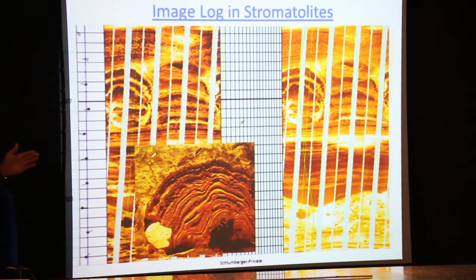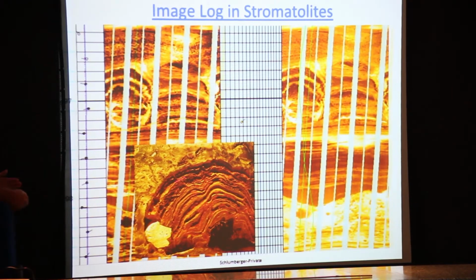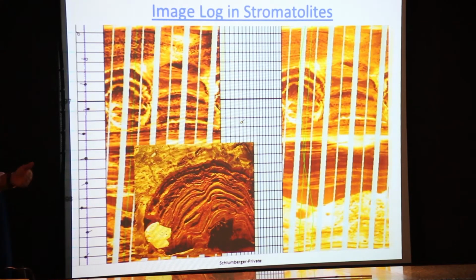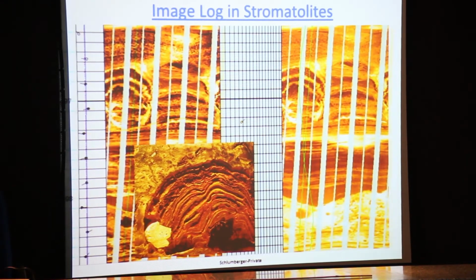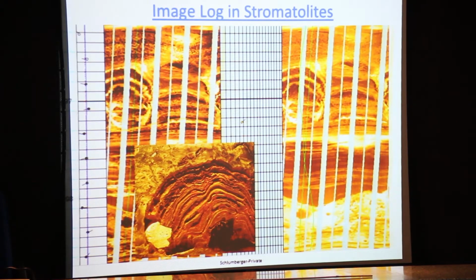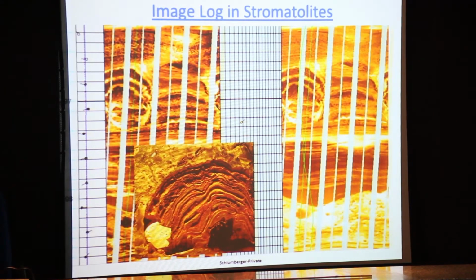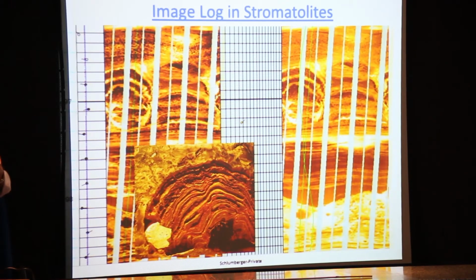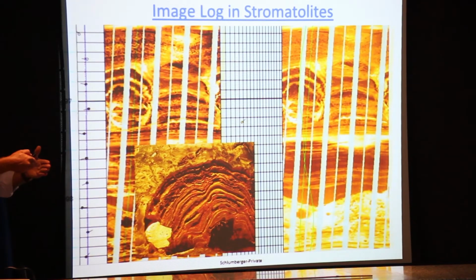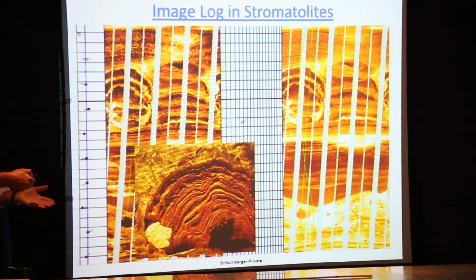There's another important effect in the pre-salt too, with the faults and the hot salt water coming up. It can actually dissolve the pore space or dissolve the calcite grains and enhance the porosity. So you get two effects. You get this arch effect helping to preserve the porosity, and you also get this acidic water that can actually increase the porosity in some zones, but eventually that water becomes calcite rich, and as it moves away and cools down, it will actually precipitate that calcite, and you will lose porosity in some areas.